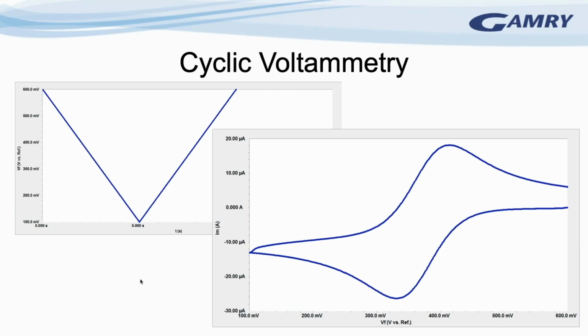And a cyclic voltammetry example is on the top right again. I'm showing the voltage profile, which looks like a V, where we have a constant scan rate going from one level to another and back again. And the bottom left is the current response, in this case for potassium ferricyanide in solution, where the current in one direction is in the positive direction, and then when we reverse the scan, it goes in the other direction. The peak occurs when we get the rate of reaction. The peak is an indication of the electrochemical potential of the species of interest. In this case, iron 2 to iron 3.